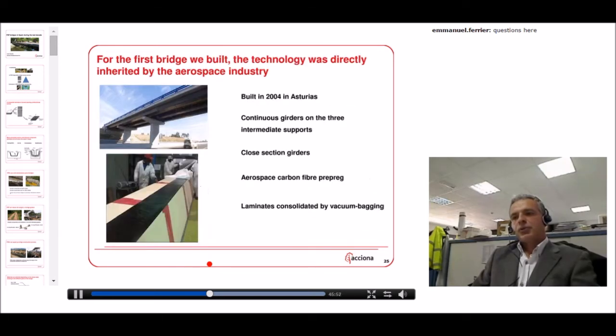As I told you, for the first application, we used closed-section girders with a trapezoidal cross-section. This is very good from a static point of view, but this obliges you to use a stay-in-place mold. The stay-in-place mold is represented here by this polyurethane mold. This means that for each of the girders, you lose the mold. And this increases very much the costs of these girders.